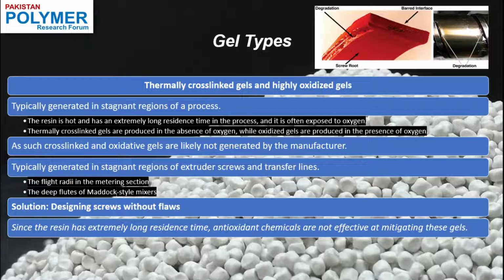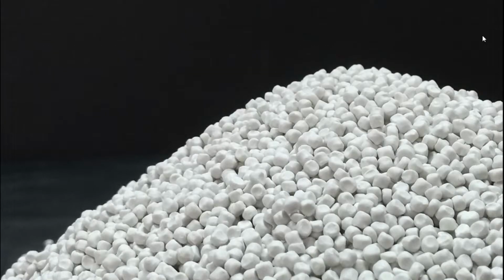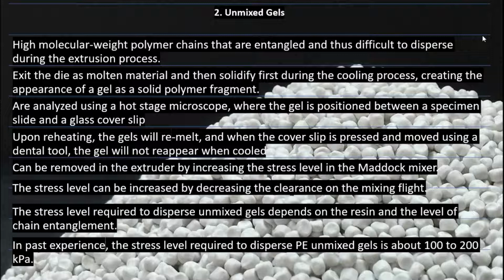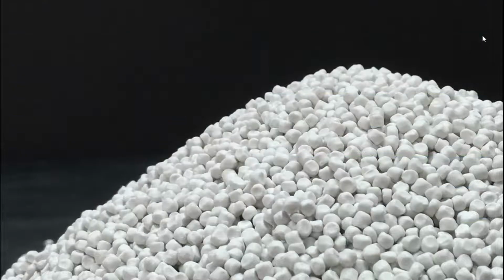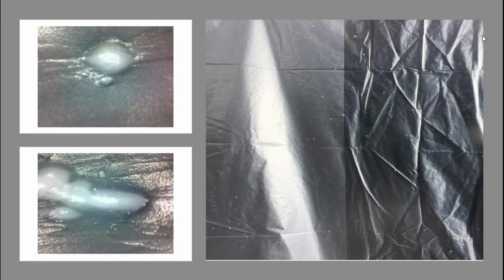Next are the unmixed or entangled gels, and this problem is more common with polyethylene resins. These unmixed gels are typically high molecular weight polymer chains that are entangled and are difficult to disperse during the extrusion process. These gels exit the die as a molten material and then solidify first during the cooling process and create the appearance of these gels.